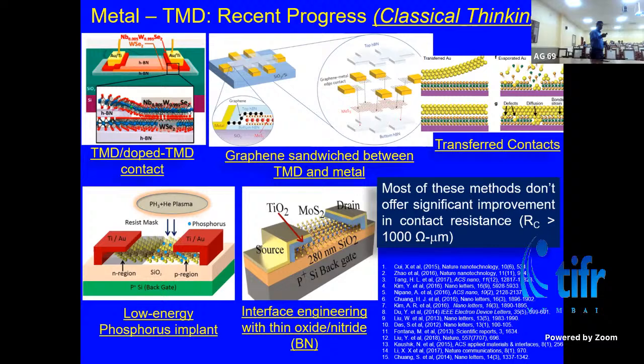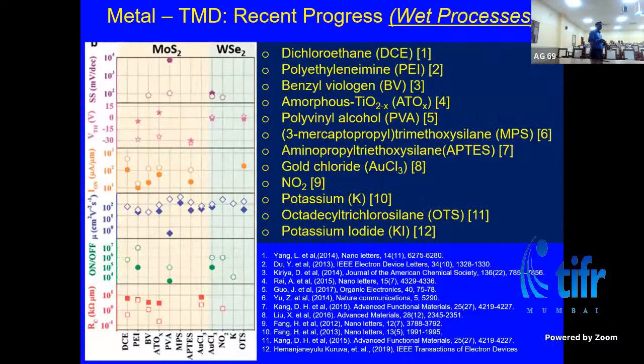So there are a lot of charge transfer methods demonstrated, and as a function of that, people showed that we can improve the contact. But from a technology point of view, you cannot scale it up, right? For example, a lot of salts were shown, pretty much every salt, you dip into that salt, you show that there is a charge transfer, and you have a better technique. So you have low resistance, and so the contacts look better.